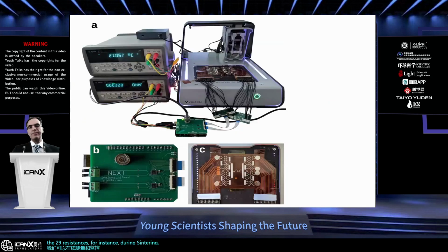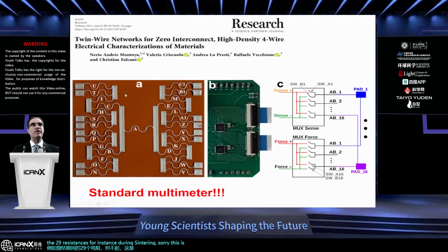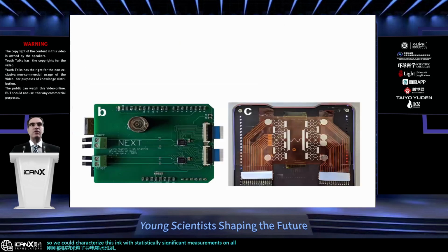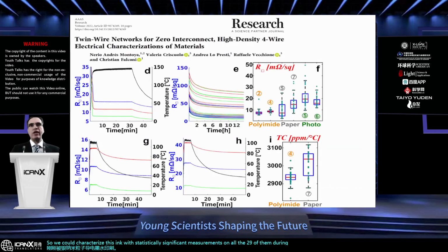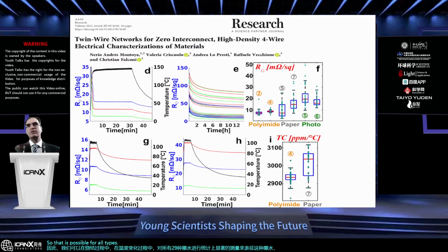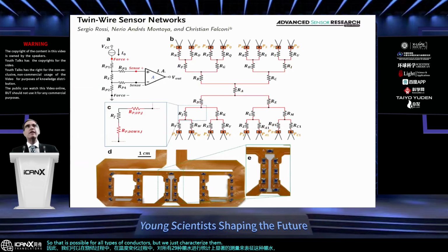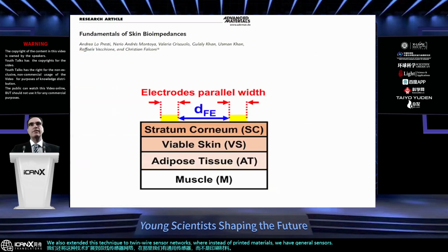This device that you see here on the left is just printed with silver nanoparticle conductive ink. So we could characterize this ink with statistically significant measurements on all 29 of them during sintering, during changes of temperature, and so on. That is possible for all types of conductors, but we just characterized this conductive ink. We also extended this technique to twin-wire sensor networks, where instead of printed materials we have general sensors. That's another paper, but I will be quick.